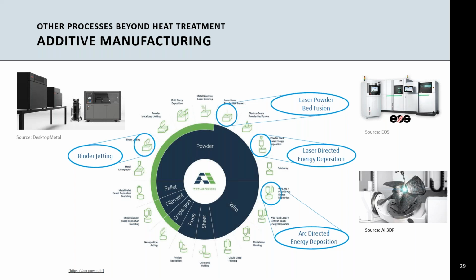Within the plasma process, the additive manufacturing is like laser metal deposition, in that the powder is guided towards the substrate in a gas stream and fused by plasma heat. Additionally, process cooling is required during this welding process, such as with CO2, to keep everything from warping and allow for an even buildup of material.